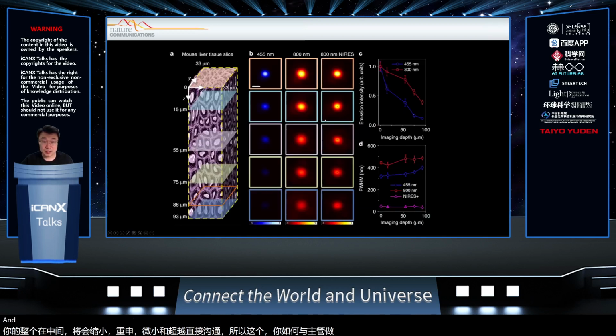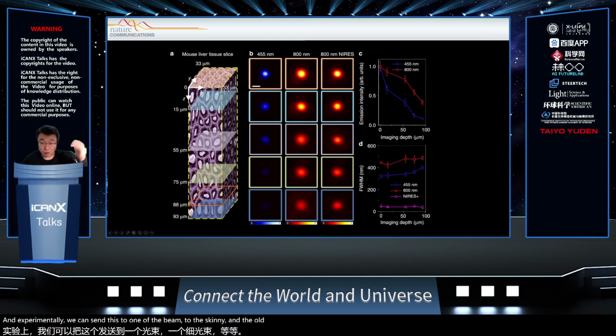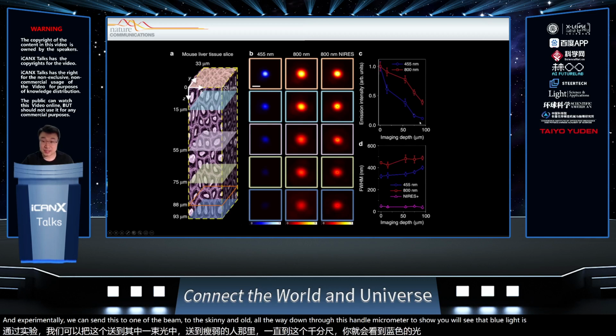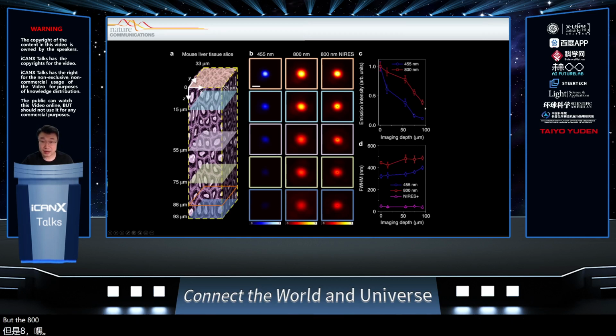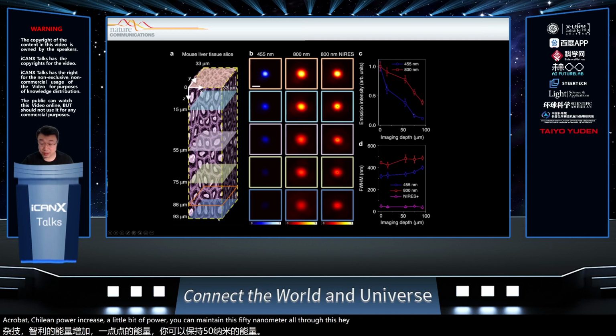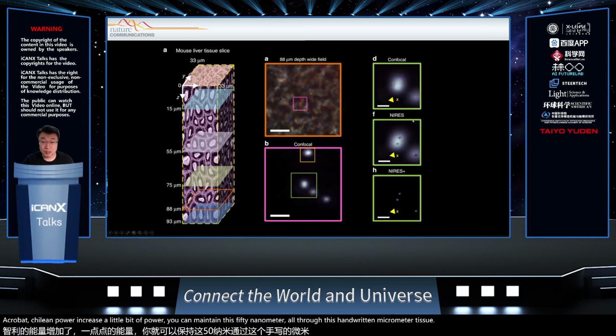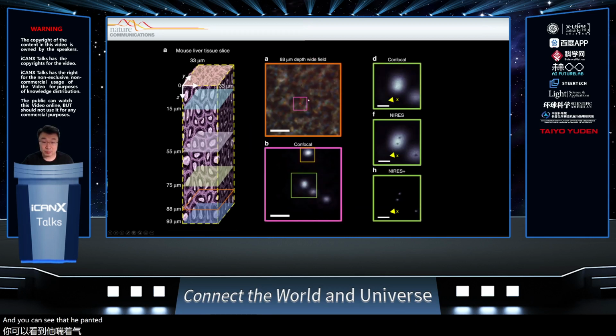And experimentally, we can send this donut beam and do the scanning all the way down through this 100 micrometer tissue. You will see that the blue light has basically already faded off, but the 800 nanometer light still has something. And amazingly, if you look at this pattern, is there a small hole in the middle? This is 50 nanometers. Actually, by increasing the power a little bit, you can maintain this 50 nanometers all through this 100 micrometer tissue.